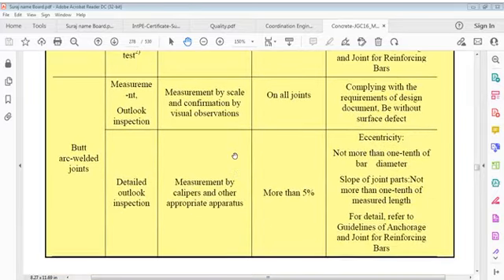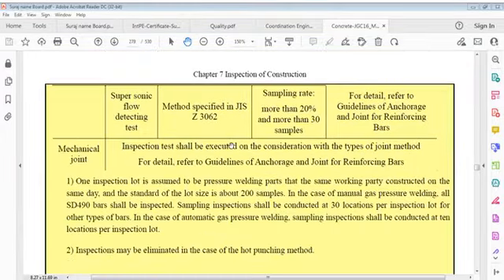We have butt arc welded joints, measurement, outlook inspection, detailed outlook inspection, measure by scale or confirmation, calipers and others. So we have all joints more than 5% here. Complying with requirement of design without surface defects, eccentricity not more than 1/10 of bar diameter. Slope of joint parts not more than 1/10 of measured length. For details, see guidelines of anchorage, joint of bars. Supersonic flow detective test method specified more than 20%, more than 30 samples, and follow guidelines for anchorage and joint.